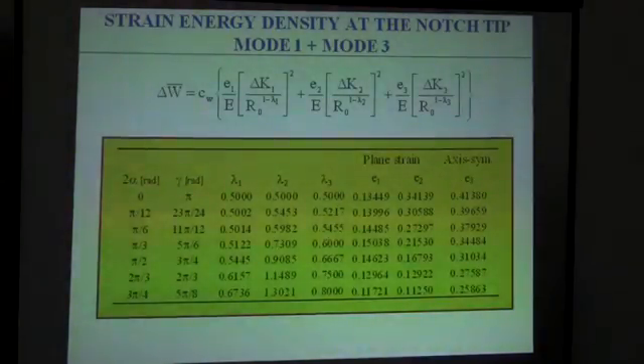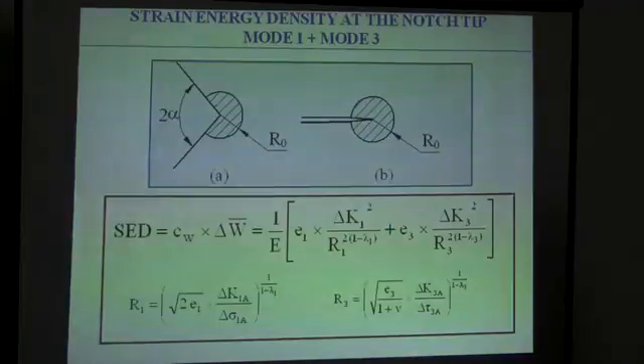And extending the criterion to multiaxial fatigue, we can introduce in the equation also mode 3 loading. In the case considered in the present work, we have only mode 1 and mode 3. And we have a simple table which reports, for each notch opening angle, the values of E1, E2, and E3, which permits us to apply the equation directly.